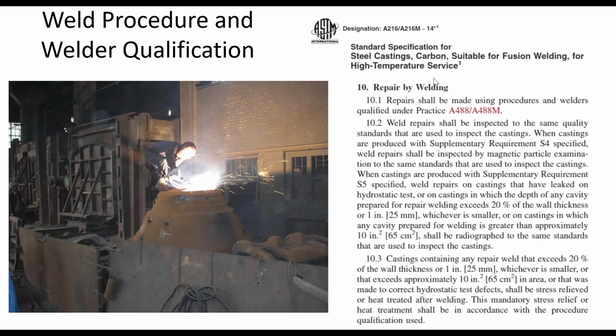We actually have to, under each specification, this is ASTM A216, which is plain carbon steel, WCB, most common alloy we make. And it says that if I repair it, I have to use ASTM A488. It says I have to inspect it to the same quality standards, and it defines how big of a weld I can make without permission and what inspection I have to do. So welding in the steel casting industry by all the commercial standards is heavily regulated.